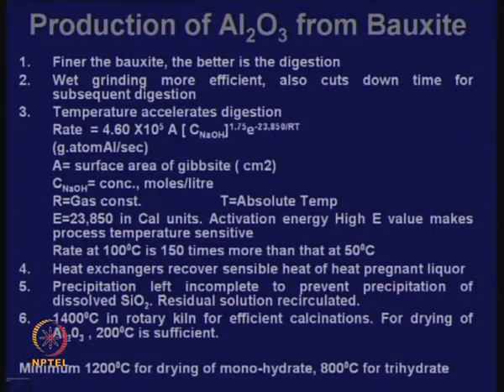It has been found that when you start precipitating by adjusting pH, etcetera, first alumina will precipitate, and silica will come later. So, the idea would be to go for incomplete precipitation, which means you do not take out all the alumina, but you take out alumina which is totally pure, because your fused salt electrolysis process will not tolerate impure alumina. If silica goes in there, it is not going to get electrolyzed. So, with time it will deposit in the cell and create havoc. We do not want that. We want the purest alumina. So, we need to prevent precipitation of silica, and we do that by incomplete precipitation of alumina.